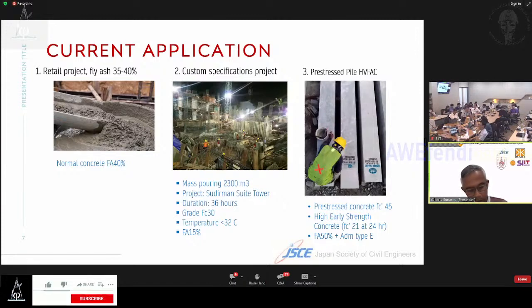Pre-stress production is limited by strength and time. Pre-stress concrete must be able to reach a certain tensile strength so that the steel cable can be released. The time required for release affects the speed of the production. So when we use fly ash of about 50%, it causes the initial strength to be slow.